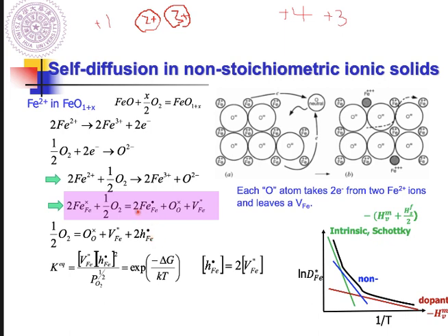These two holes means this hole, one positive charge times 2, so you also have one positive charge times 2. So you got this equation. Based on this equation, we can formulate the equilibrium constant under the equilibrium condition as this times this divided by the partial pressure of oxygen. And don't forget the order is 1/2. And for this times this, the order is also 2, put here.